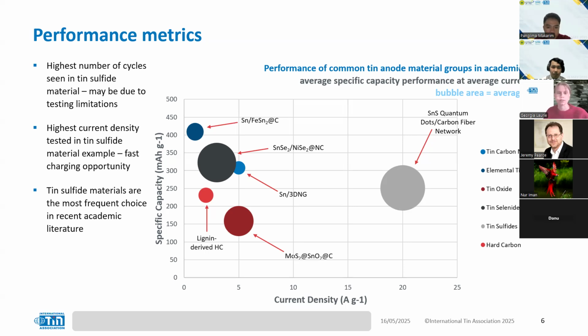It's also important to note that in recent academic literature, the most popular choice for tin anode materials has been tin sulfides. The most number of papers on tin anodes have had a tin sulfide material as the example. Also on the graph, we can see that on all of the different tin examples, there is actually a form of carbon being used in the anode material as well, which actually does identify that carbon is integral for helping stabilize tin anode materials and buffer volume expansion during cycling. So tin and carbon are really often used in conjunction with each other.